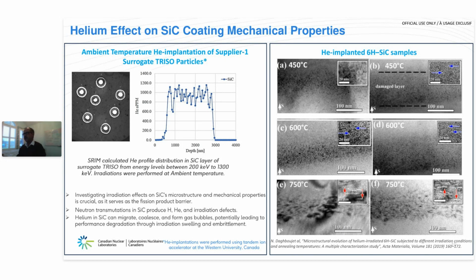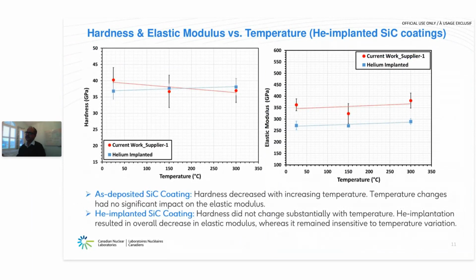And we used these helium implanted samples with 50 millinewton loads to the maximum depth that was reached. We found that the plastic zone of the maximum depth was covering this 1 to 3 micron depth of the damage, or the helium implanted zone, as predicted by these SRIM calculations here. And the results from as-deposited and helium implanted supplier one coatings.